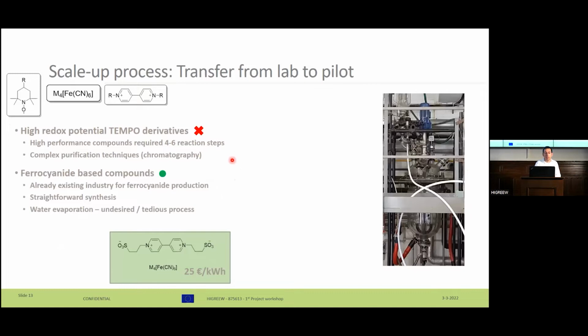So here, when turning into the part of TEMPO derivatives and ferrocyanide, the TEMPO was discarded because it requires a really long, quite long synthetic route with 4-6 steps, which at this level is making the cost of the electrolyte high, and it was including as well some purification techniques such as chromatography. This does not mean that this compound is not good or valid. It means that we have to readapt the synthetic route to make it cheap or feasible.